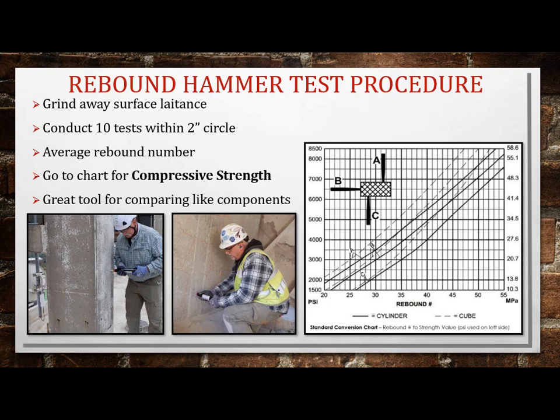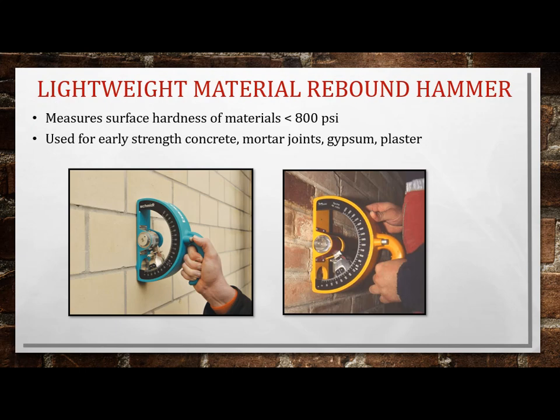It's really, really convenient. Roll it over, and you can do it. And so on this particular one, say your average was a 40, you go up, over to the left. So rebound number 40 is equivalent to like 5,000 PSI on the B scale. So gravity affects these. If you're doing it on a wall, you go to B scale. If you're doing it flat, you use A scale. Overhead would be C.